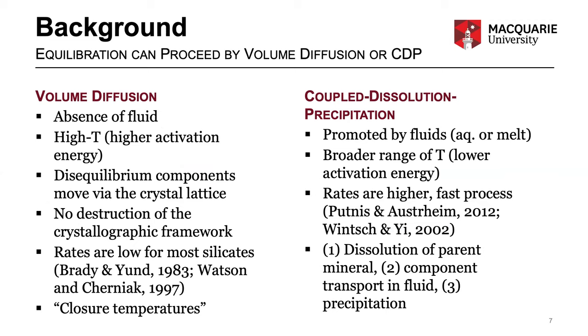The process of coupled dissolution precipitation needs to be contrasted with volume diffusion. This is because researchers who use geochronology, like me, tend to think about closure temperatures in terms of volume diffusion. And so this happens in the absence of a fluid. It has high activation energies and therefore happens at high temperatures. The components move via the crystal lattice, and there's no destruction of the framework, and the rates are actually quite low for most silicates. In contrast, with coupled dissolution precipitation, the fluid lowers the activation energies,